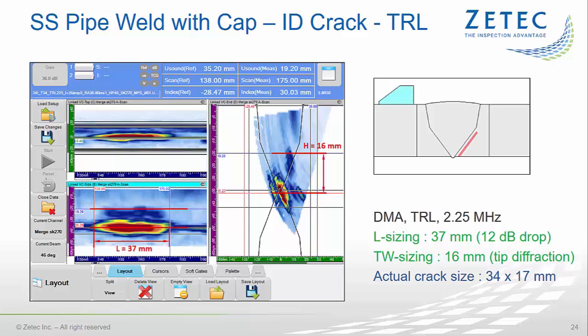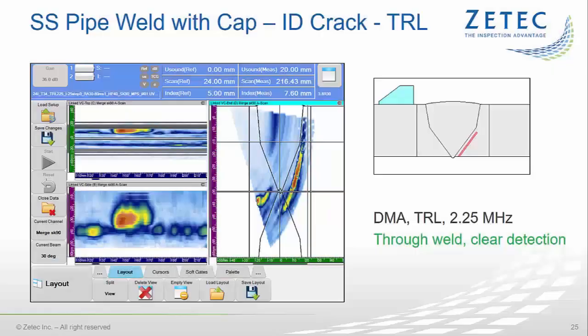As shown on the slide, the center of the highest clearly resolved signal should be taken into account for through-wall measurement. This is where the measurement cursor is positioned, and now the crack depth can be read from the information views. And finally, let's look at the L-wave examination from the other side of the weld. The crack is now on the far side and can still be clearly detected by adequately positioning the projection gates.